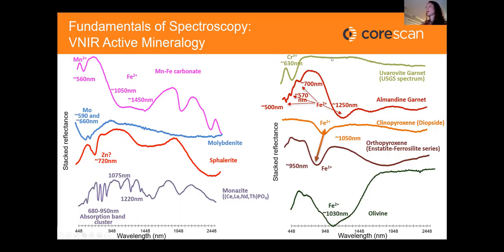Over here on the upper right are some examples of garnet reference spectra. As we start including chromium, manganese, and iron into our garnets, we have diagnostic absorption bands in the VNIR. We can differentiate between ortho and clinopyroxenes using iron features located at about 1,000 nanometers. And the same goes for olivine. It also has an iron feature at around 1030 nanometers.